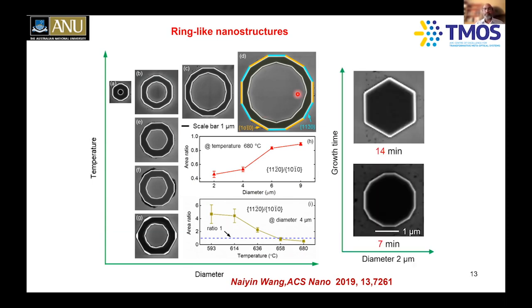So we keep on growing, and then you end up filling this gap here. You end up creating these horizontal membranes here. And then, of course, if you keep on growing, you finish off with these nice hexagonally faceted structures, because crystals always like to grow into the low energy facets, and that's what it creates. Now you can see I've shown you vertically standing membranes. Now I'm showing you horizontally oriented membranes. For MEMS applications and other things, we may want to make use of them, including ring resonator lasers and other things, which I will come back to and share with you.